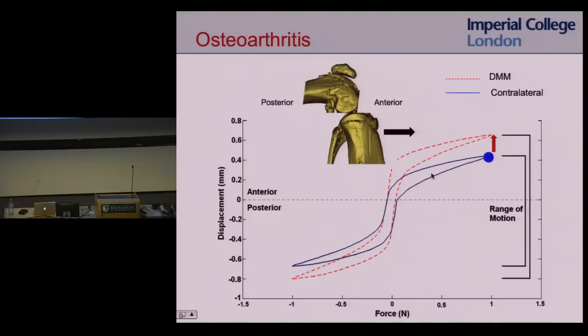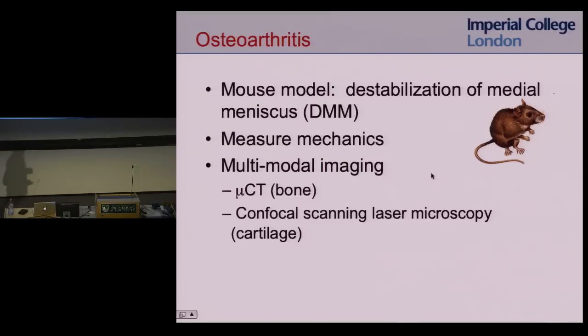So if we give the injury, and it can move forward more anteriorly, that means the femur, which is this bone up here, is sitting on the back part of the tibia. So we might expect to see most of the damage on the posterior portion of the tibia. So let's take a look and see where the damage occurs. We use multimodal imaging to look at what's happening. We use micro CT to look at the bone, and confocal scanning laser microscopy to look at the cartilage.